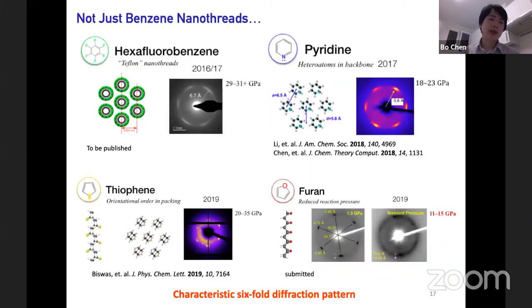And it's not just benzene that gives nanothreads. Over the years, we have found that other types of small aromatic molecules, for example, fluorinated benzene, pyridine, furan, thiophene, they all form nanothreads under pressure. The pressure can be different, but the important thing is that they all give this characteristic six-fold diffraction pattern that can only be matched by the simulated pattern for a nanothread crystal. And the d-spacings can be larger than benzene in this case, similar to benzene in this case, and smaller than benzene. This depends on the size of the ring, and all the numbers make sense.